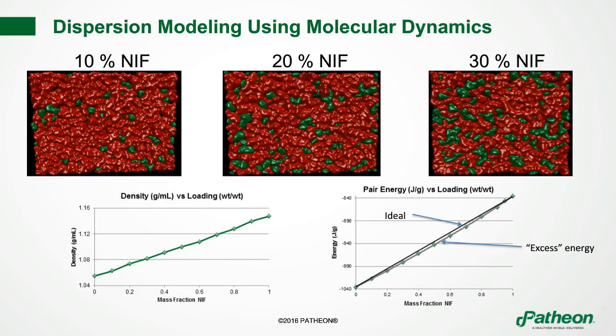Now, the other thing to mention here is just because you have drug molecules that are agglomerating together does not necessarily mean that that's bad from a performance perspective. Now, we don't want to see agglomerates because that can lead to nucleation sites and recrystallization. However, if the kinetics of that are incredibly slow, which they typically are in a dispersion, then that might be okay. And in fact, if you have agglomeration sites but still amorphous in nature, so the drug is not actually crystalline, it's amorphous, well, when those are released into water upon submersing the entire dispersion in an aqueous environment, you still would see very good performance. And that's what we're aiming for.